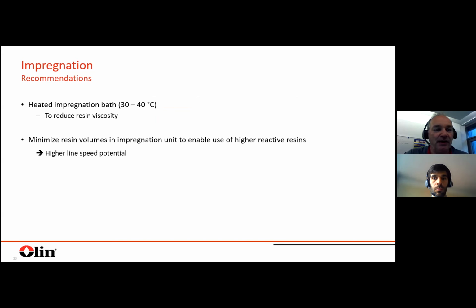So one other option for sure would be to operate with a heated impregnation bath. Just by this, you can reduce the resin viscosity, and this will simplify the impregnation. And you can also minimize the resin volumes in the bath or in the impregnation unit. This would really open the door to use more reactive resins. And then for sure, you also have higher line speed potential.